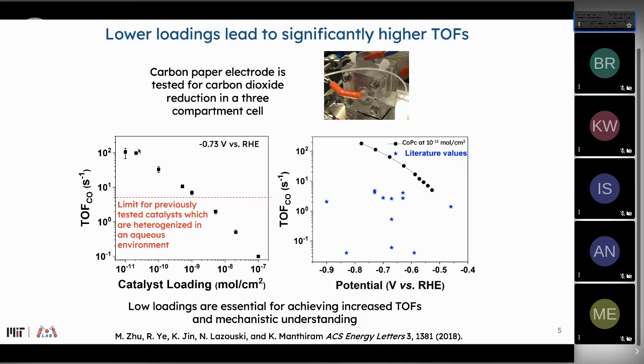It's important to emphasize, though, that this comes at the expense of current density. So if you're trying to make the world's best electrolyzer, this insight by itself doesn't tell you much, other than that one is not maximally utilizing their catalyst at the typical loadings that are used. There are many innocent bystanders. Perhaps only 1 in 100 or 10 in 100 of the catalysts are actually being utilized. The rest have inaccessible active sites that make them bystanders for this reaction.